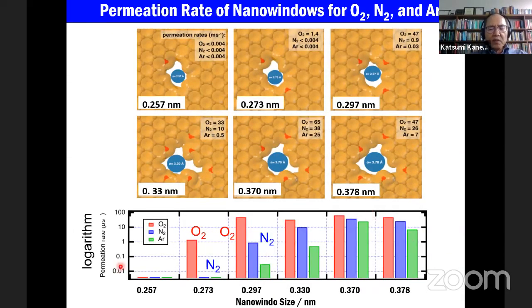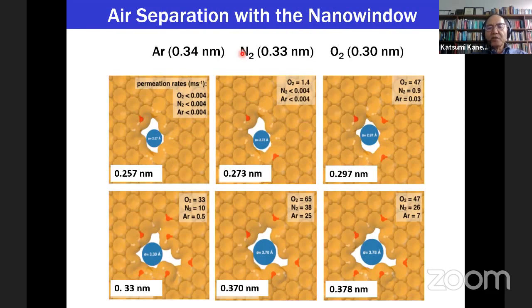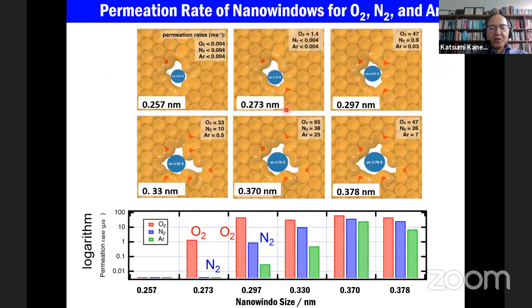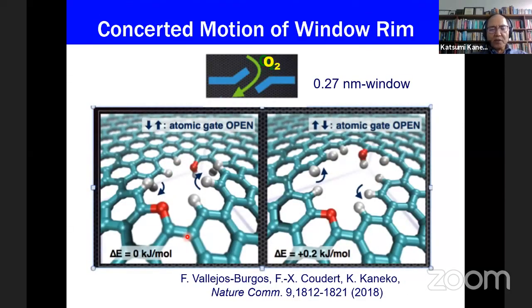Then here we compare the oxygen, nitrogen, and argon permeation rate. Even the 0.273, this one can permeate, but the oxygen, depending on the model, the size 0.30 nanometer, but this 0.27 nanometers, almost only, not necessarily only, but slight nitrogen, but almost oxygen permeates. A very high selectivity is obtained.